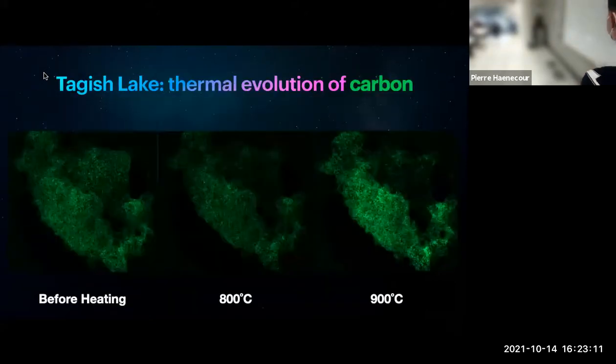And then if we look at the elemental composition for the 3 different steps, I didn't show you the 1,000 degrees because it basically showed the same trend as 900 degrees. But as you can see, the carbon signal became stronger and stronger. And what we saw is basically showing that you go from amorphous carbon, like organic matter, or aromatic carbon, to graphitic carbon. So you basically graphitize the organic matter in your sample as you heat it up.